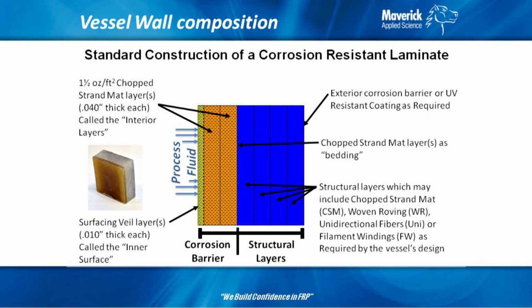So a little bit about how stuff is made. Typical fiberglass laminate. If you assume this block here is basically this, the first yellow layer is the veil layer. And that surfacing veil, again, is holding so much resin up against the process fluid that that's what provides your primary containment of the fluids. This is going to have 90% plus resin. The following layers, which are typically chop strand mat layers, either sprayed or rolled goods, are going to have 65 to 70% of their weight in resin, depending on how well it's wet out. So you can see as you go through the structural wall, the amount of resin in the laminate gets lower. And as you go back through the secondary structural layers, those layers can have only 35 or 40% of their weight in resin.